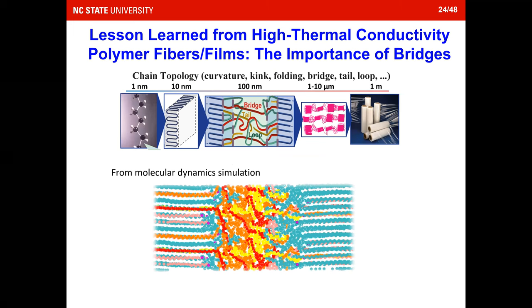And then why is that? The current model actually does not account for the differences between the amorphous materials and the intercrystalline parts. So we want to ask, can we actually try to understand this at the molecular level? So my students did molecular dynamics simulations, and we're trying to see the contributions of those bridge chains. As you can see, I show in the middle, there are bridge chains in red.